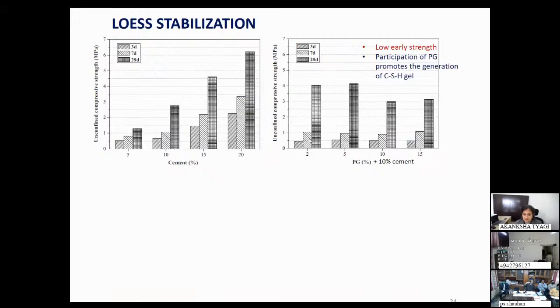So when I say the early strength is decreased or not high, but the final 28 day strength is higher, the thing is basically that the setting time of the cement is getting prolonged. But at the same time, you will see the strength has increased. It is because the participation of phosphogypsum promotes the generation of CSH gel. It is again due to the mineral I already told you about, ettringite. The needle-like ettringite forms a kind of framework and fills the inner voids of the samples, and it increases the strength. But if there is excess ettringite and it is not able to react with the cement, then this excess ettringite will cause excess volume expansion, and that is why the strength has reduced.